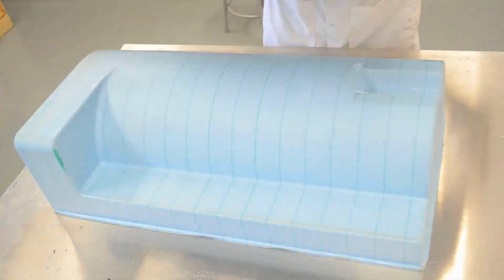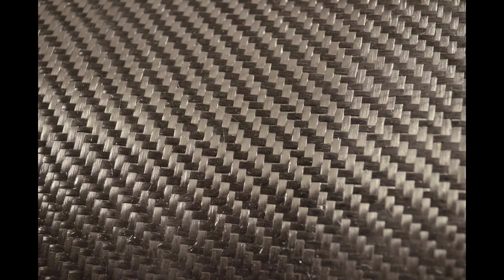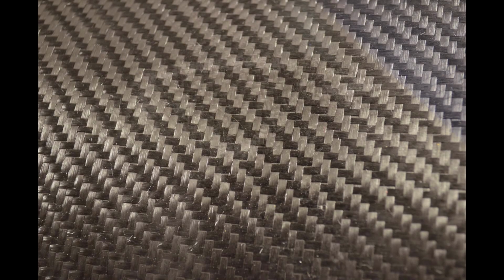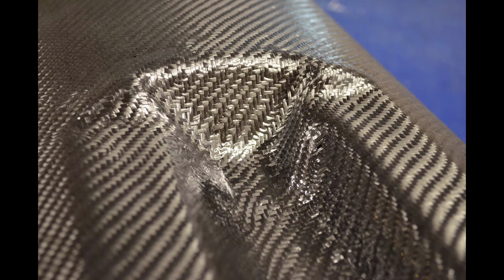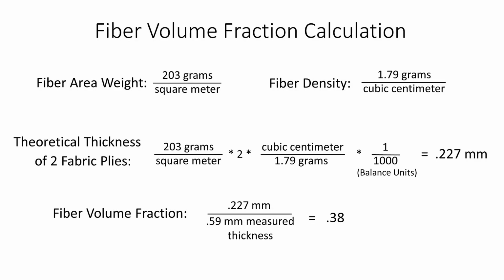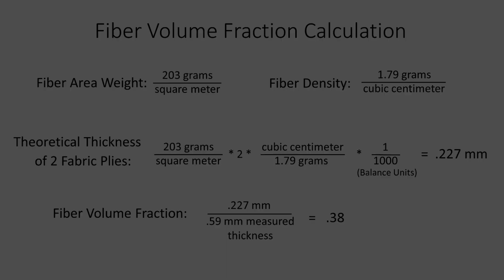After removing the part, we can see that it is generally well saturated but has a few small dry spots. The inside surface has some porosity throughout. The outside surface is quite consistent but is not smooth. The tows of the fabric are noticeable and have created a patterned surface. A fiber volume fraction of 38% was calculated, typical for a wet layup cured without a vacuum bag.